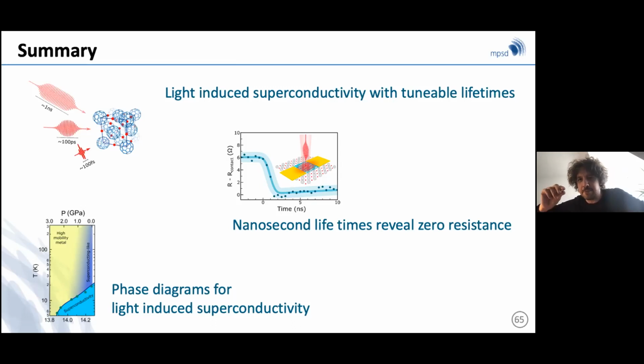But maybe just to follow up, is the picture that you have this valence bond type of states which build your bosons, where the spin up and spin down bind? And via your pulse, is it basically that the binding energy of this two-body state becomes stronger and thereby the gap increases? It could be. Actually, that's something I said a little bit in passing. When we looked at the data, we said this gap is twice as big, for sure. On the other hand, if you look at the spectroscopic features of C60 itself, what you find is that there is a polaronic peak that starts rising. And so whether we're really seeing the gap or the gap is maybe much larger even, I don't know.